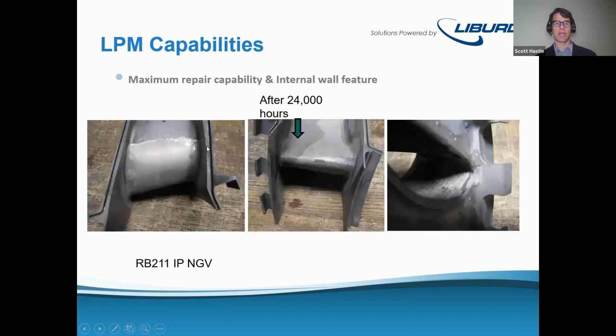And so now we'll look at the repair. This was a really exciting one that came back to us after 24,000 hours. You can see inside here where the internal geometry of the ribs moved from the base alloy into the LPM alloy. But the really exciting thing here was 24,000 hours, no cracks, no deformation, no damage, and we just recoated the part and put it back into service for the next 24,000 hours.